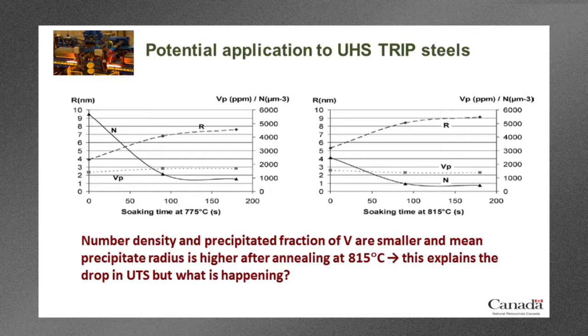So what you have on them is from TEM data and a combination of TEM data and from these selective chemical dissolution experiments where we could get the total amount of vanadium precipitated. And you can see, for example, here we have a number density. So at 0 seconds, we have a very high number density of vanadium carbonitride precipitates. And as we go into the intercritical annealing soaking, that number density actually tends to decrease. The mean radius is very small at the beginning, and it's actually growing. And the total amount of vanadium precipitated is fairly constant. There's a small increase in there.